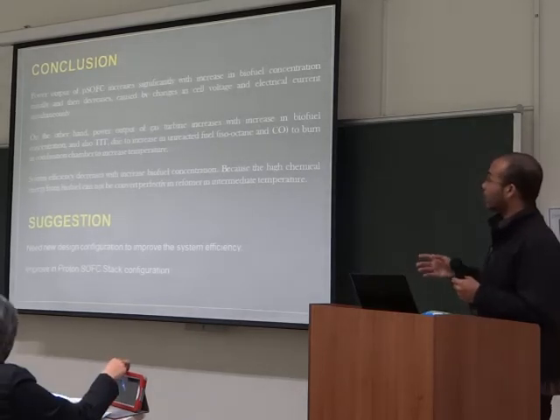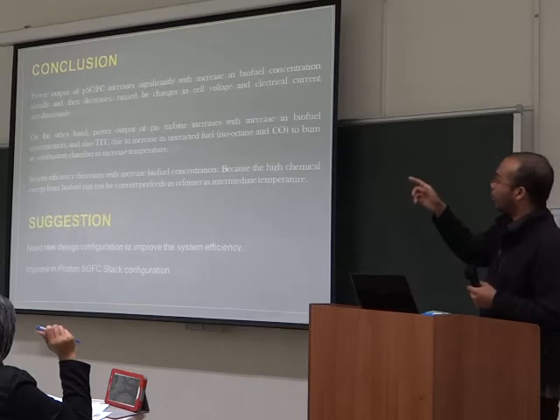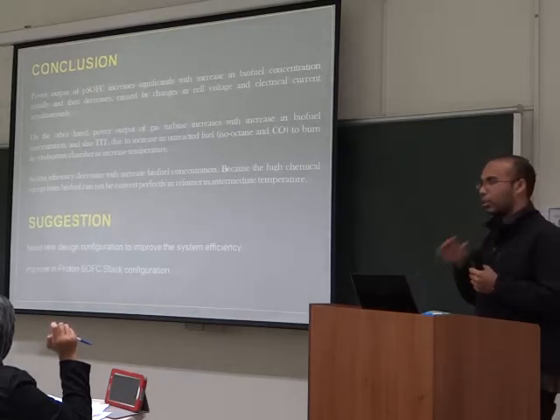And this is my conclusion. First, the stack power increases with increasing biofuel concentration up to 40% and then decreases. But for TIT and gas turbine power, they increase with increasing biofuel. Unfortunately, the system efficiency decreases with increasing biofuel concentration.